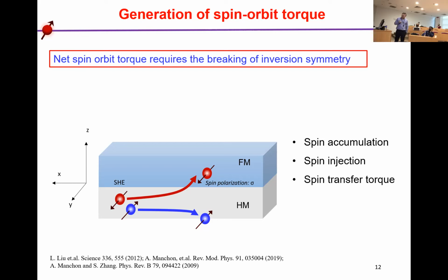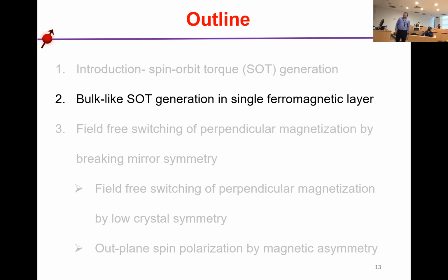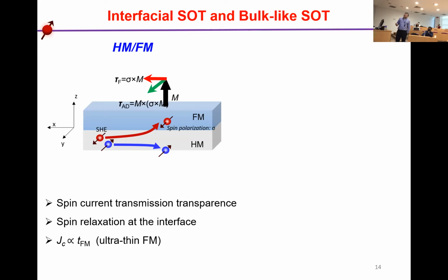But from here, we can say when the spin current is injected into the ferromagnetic layer, there are some consequences, for example, spin accumulation, spin injection, and then spin transfer torque exerted on the ferromagnetic layer. So the efficiency in the bilayer structures will depend on the interface properties. For example, the spin current transmission transparency is very important, which affects the SOT efficiency significantly, and the spin scattering or spin relaxation at the interface will also affect the SOT efficiency. Another one is that due to the spin current spin polarization dephasing in the ferromagnetic layer, this can only be used for ultra-thin magnetic films.